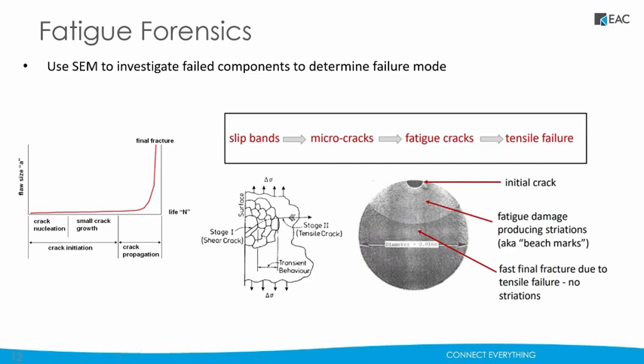Take a failed product, put it in an SEM, and actually show, especially if it's steel, you should be able to see the beach marks and fracture, crack growth, and find striations maybe down to the micro level, and then finally fast fracture at the end. And so sometimes a picture's worth 1,000 words. You can for $100 give an SEM on a failed part, and then put a picture to the actual mechanism. And that's a good precursor to say, okay, now that we know the mechanism, let's start simulating to predict it so it doesn't affect us adversely.